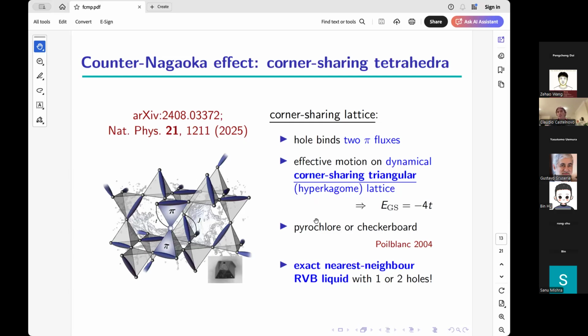Interestingly, and again, this is the third coincidence in years, this minus 4t was observed by Didier Poilblanc in ED simulations on the corner-sharing triangular lattice back in 2004, which are remarkable because at the time, well, he was a master of exact diagonalization and numerics and was able to do system sizes that we still have a hard time getting to today without his expertise, put it that way. And he showed that you get exactly minus 4t with a single hole, minus 8t with two holes, but we'll come back in a minute. He suspected that an exact number in physics doesn't happen by chance, but there would be an underlying mechanism, but didn't have an explanation for it.